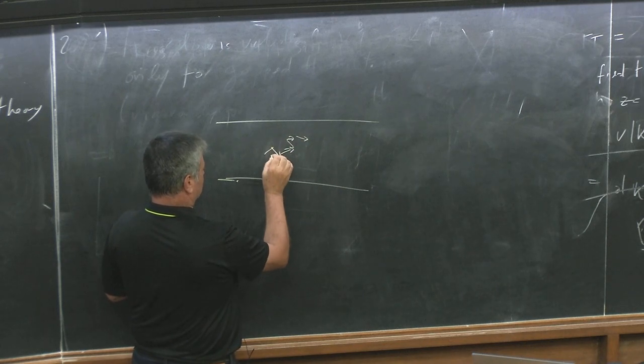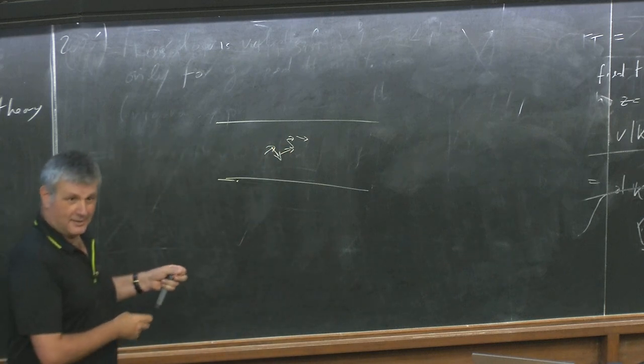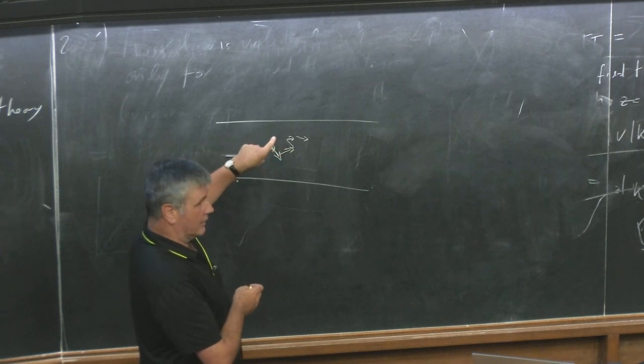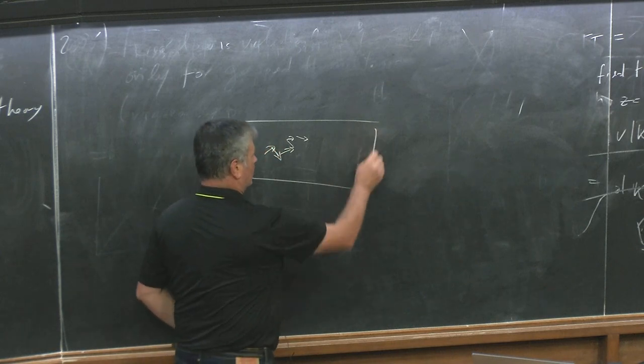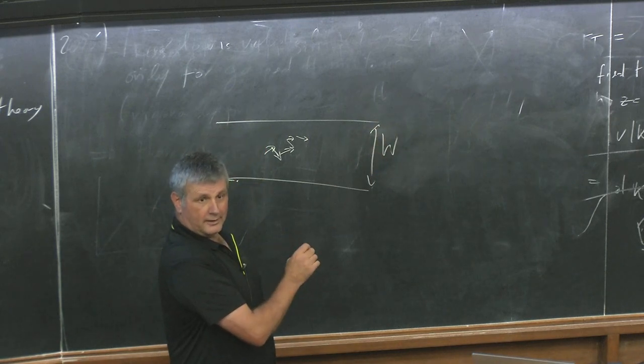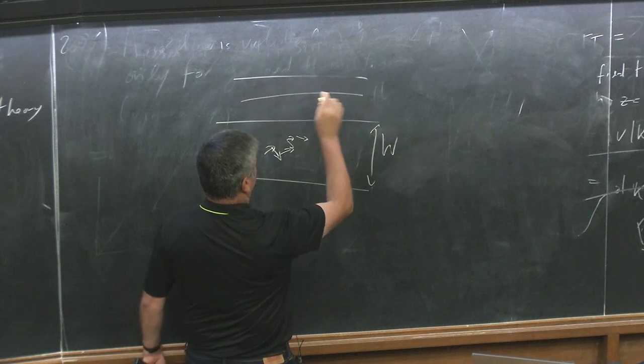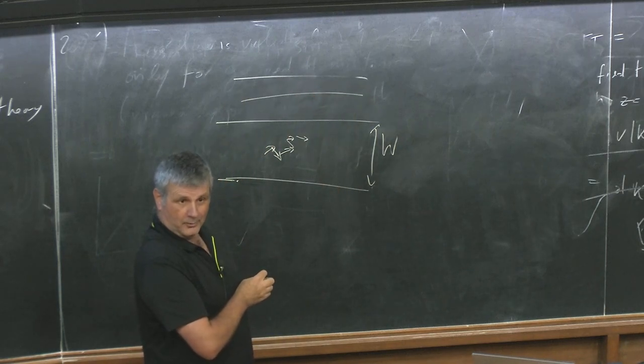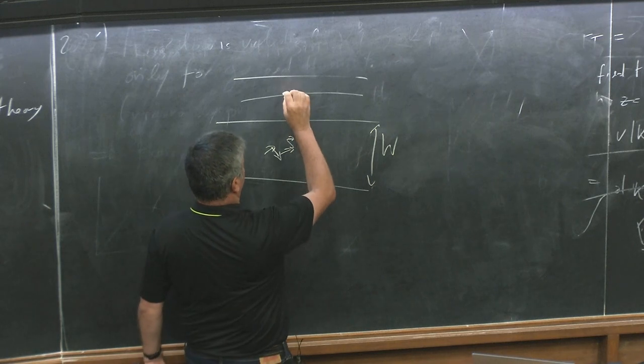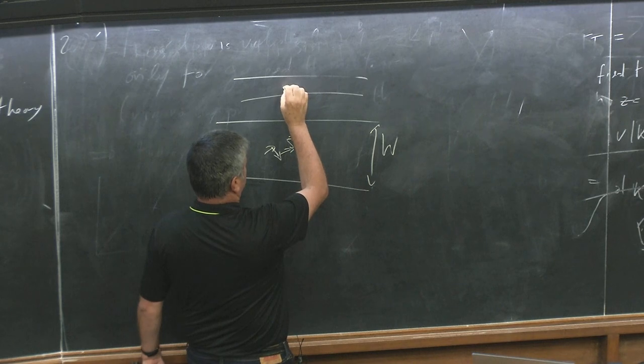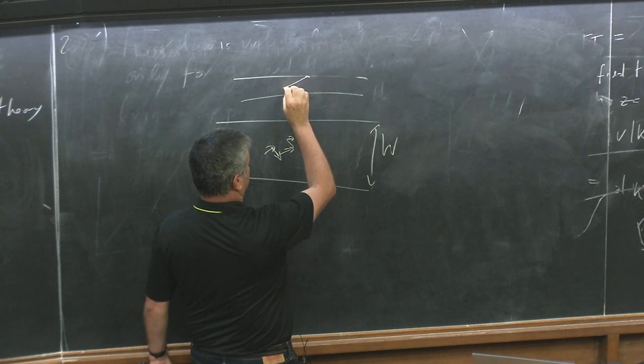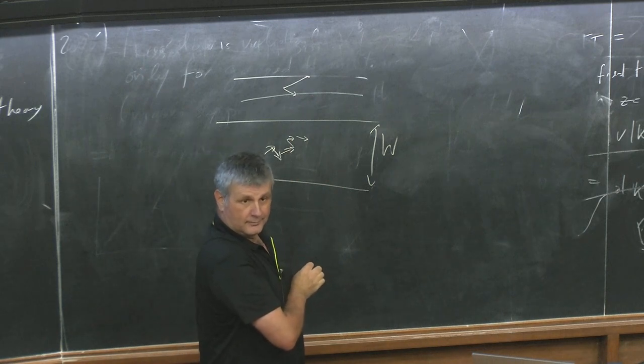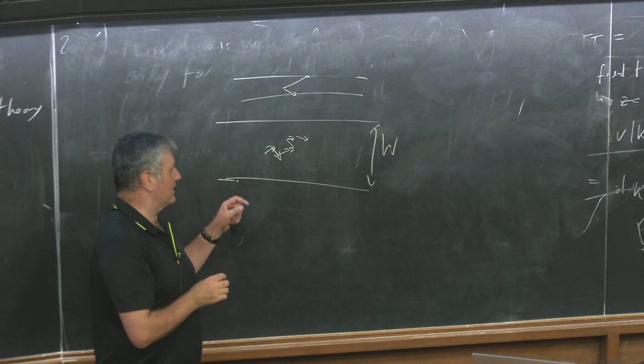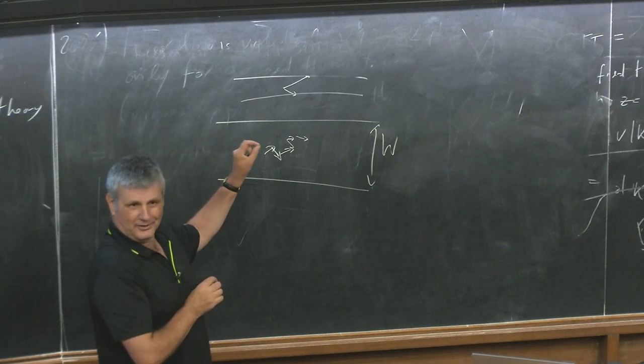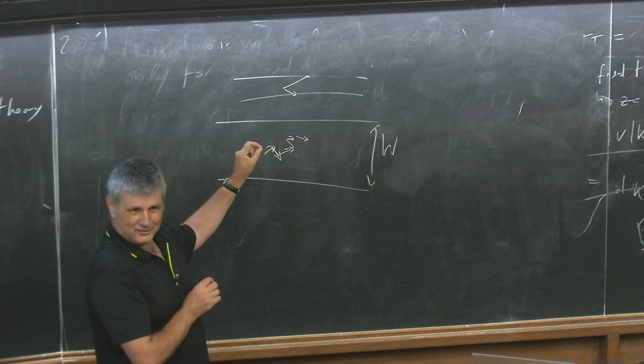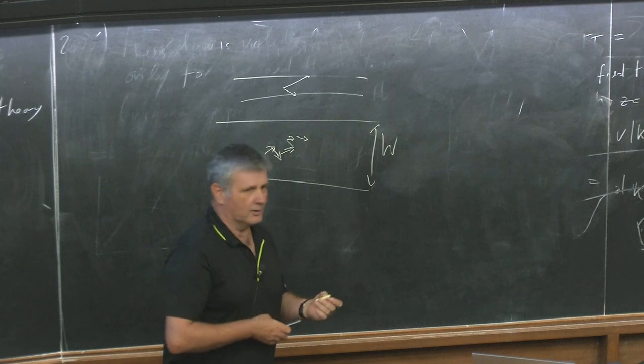internal momentum relaxing collisions. As soon as I draw on the board, you see why I PowerPoint my slides, right? And so that you've got a lot of scattering going on inside your wire on the scale of your width. If you get into the regime where you make your wire so narrow that none of the internal length scales is shorter than the wire size, then you're in a regime called a ballistic regime where you get these effects where an electron between scattering events is always going to find a boundary, basically for almost every direction it's on. Okay, and that's an interesting but different non-hydrodynamic regime of transport.